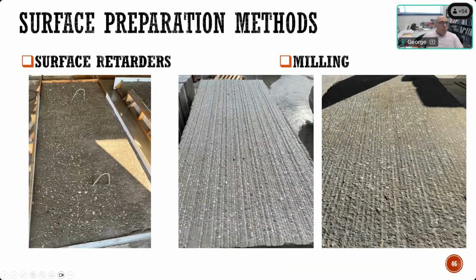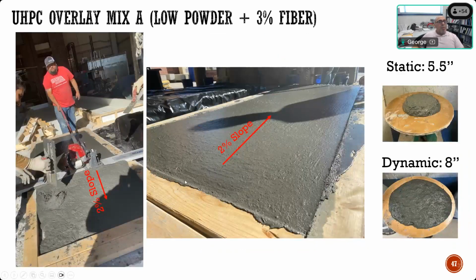And we looked at different ways of surface preparation. If we talk about a new bridge deck, we can do a surface retarder, so we can expose the aggregate. If we're looking at an existing bridge deck, we can do milling, and we tried two different patterns of milling, the typical one and the finer one, to see how much bond you can get with UHPC when you do this type of milling. So we did the specimens, and we developed the mix first, and we cast it at 2% slope. And let me just show you a video.